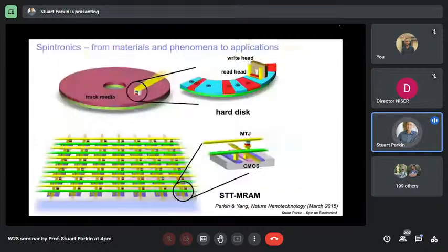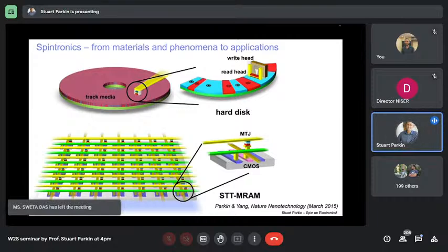This is what we call the spin valve sensor, and which we incorporated into magnetic disk drives. And this was actually in 1997. IBM introduced this spintronic sensing device into magnetic disk drives. And of course, the concept of the spin valve we came up with because of the original work by Peter Grunberg and Albert Fert, who discovered giant magnetoresistance in a set of iron chromium multilayers grown by molecular beam epitaxy at low temperatures.